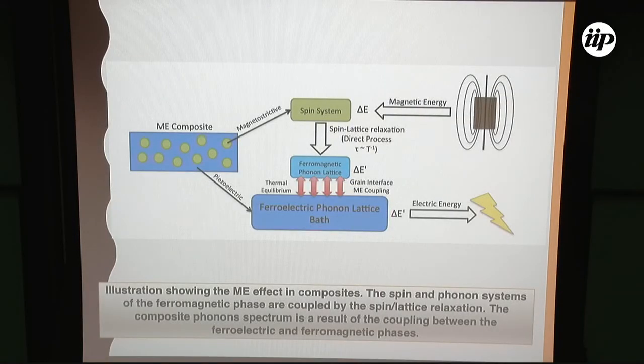The idea is that this effect is associated with this. A magnetoelectric composite is made of grains of magnetostrictive, ferromagnetic material, with a piezoelectric environment around each grain. When a magnetic field is applied, the magnetic energy is coupled to a spin system via the magnetostrictive effect, and a process of spin-lattice relaxation appears, associated with the ferromagnetic phonon lattice and the phonon lattice bath,